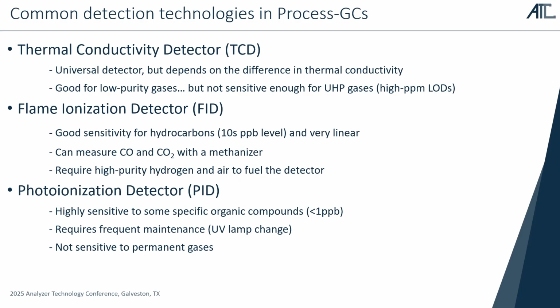There are some very common detectors in the field of process GCs. For example, you would have the TCD, which is a very common detector, but not really sensitive enough for applications in the field of high purity gases. You also have detectors like the FID and the PID that are really sensitive to hydrocarbons, but they cannot measure the permanent gases, which are key impurities in high purity gases, with the exception maybe of CO and CO2 that you can measure with a FID, but you need to use a methanizer, which can be costly and require a lot of maintenance.